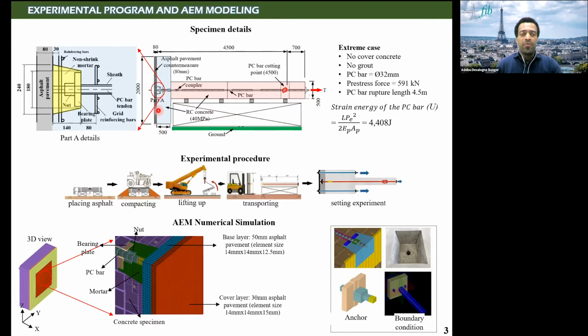So asphalt pavement countermeasure is provided here to consume all this impact energy from the PC bar. This is the experimental procedure: placing asphalt pavement, compacting, lifting up, transport, and setting the experiment like this. So we made numerical modeling as per the experiment. In this research, two asphalt pavement layers were utilized as a countermeasure. One is a base layer with 5 centimeter thickness and a cover layer with 3 centimeter thickness.